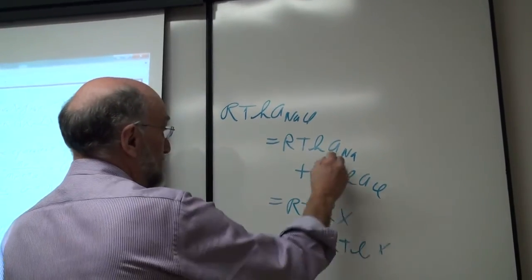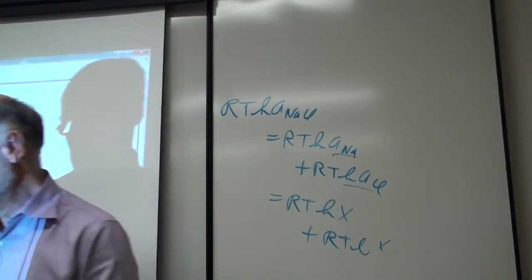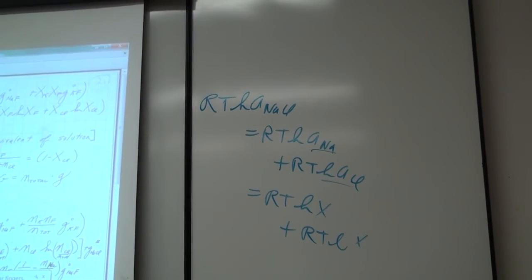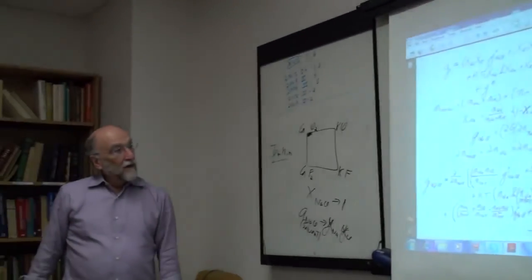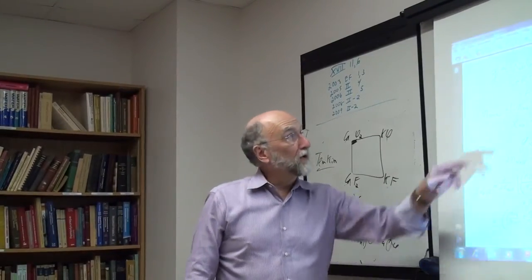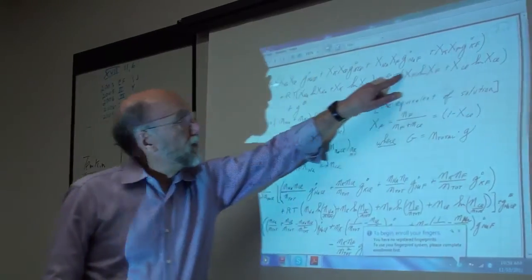This isn't quite right because you really can't talk about the activity of a single ion. But okay, so this is simply Raoult's law for a sublattice model. And Raoult's law, as you know, simply says that as you approach the pure component, the only term that counts anymore is the ideal mixing term, because the ideal mixing overshadows any second order effects you might have.